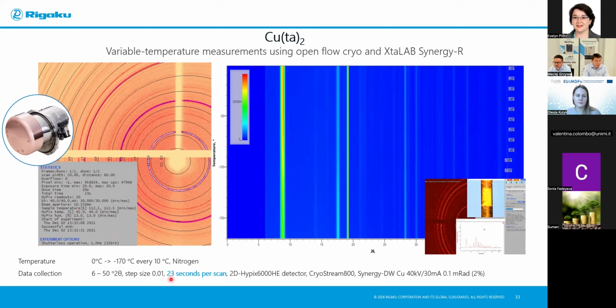23 seconds per scan per temperature. It's because the single crystal instruments use extremely large detectors. So as you can see, we collect data from almost complete Debye rings. So we have the advantages of the area detector, because this is how detector instruments are built. Here in the corner, you can see how quickly the data collection is done and how we use the Hypix detector. It's a small amount of the sample enclosed in a Kapton tube that will just spin and collect data.